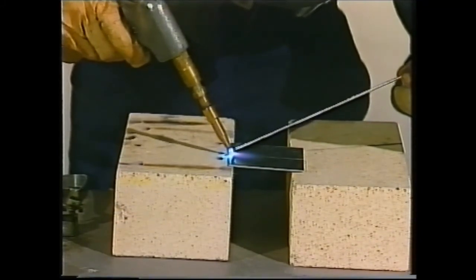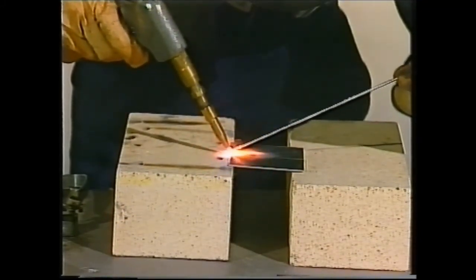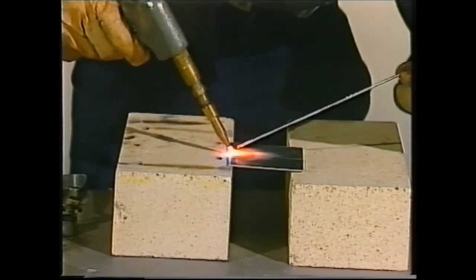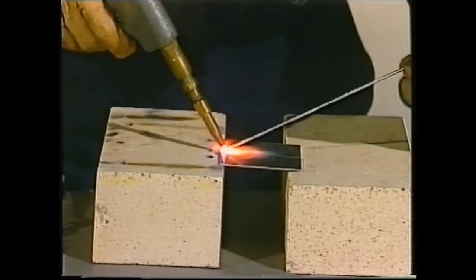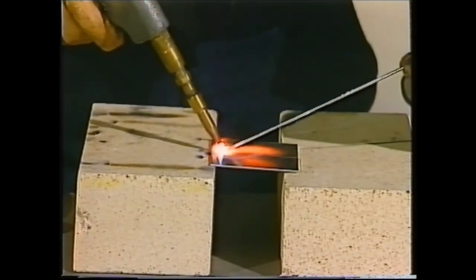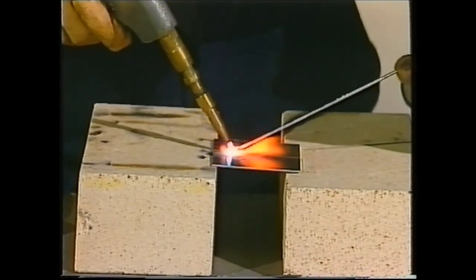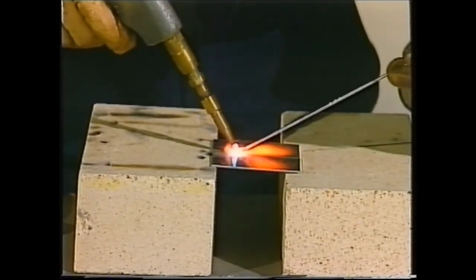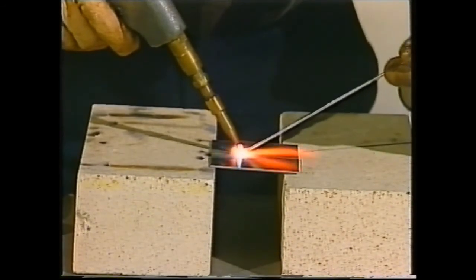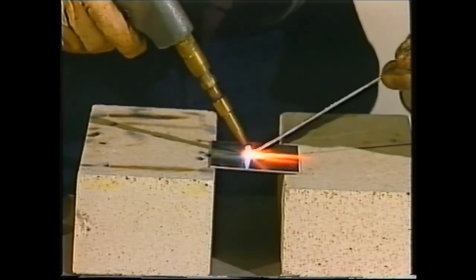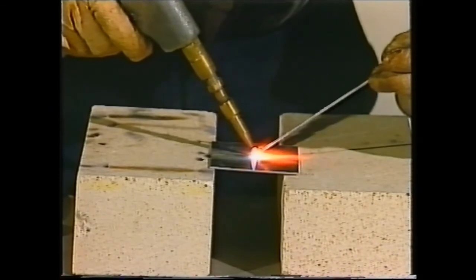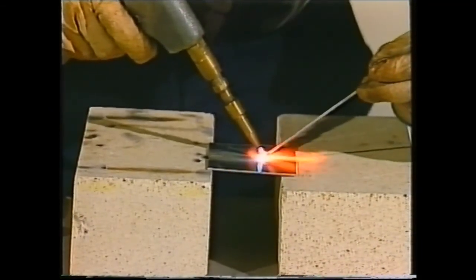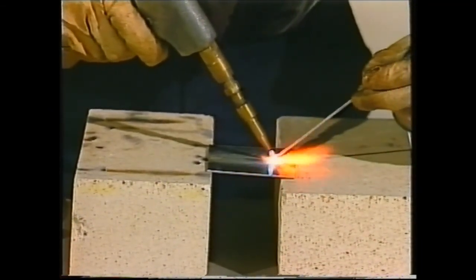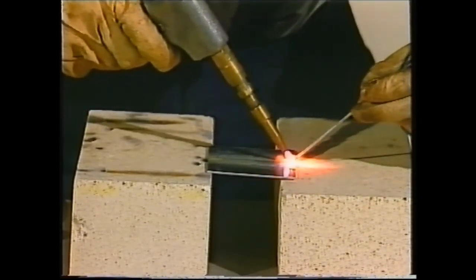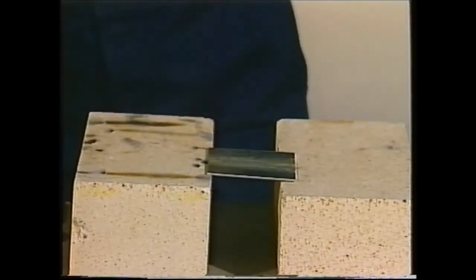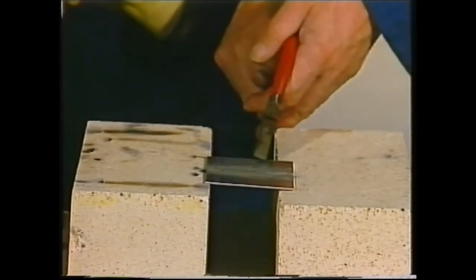Now watch the control of the torch on thin aluminium. If you were holding a conventional oxy torch on that 1.6 mm aluminium, it would be a molten mass at your ankles, probably about now. But the torch is very, very controlled, and you can see you hold the torch about 20 degrees off upright and push the filler rod under the flame and out of the way of it again. That is the technique with the torch. Now I'll just cool this off, if you bear with me a moment, and then bring it back up and show you it.